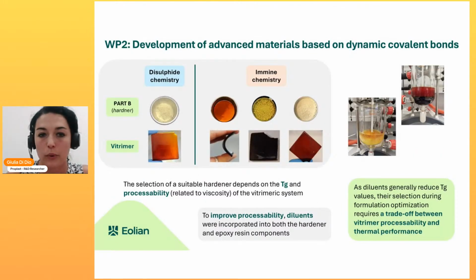Regarding our activity, we were able to synthesize several different hardeners that showed different properties, and to produce the corresponding vitrimers, which, as you can see, show different colors, flexibility, and properties. The selection of these hardeners depends mainly on two parameters: the Tg values, and of course the processability, which is strictly related to the viscosity of the vitrimeric system. This is very important since the manufacturing of the composite panels is made by vacuum infusion, which requires a good viscosity.